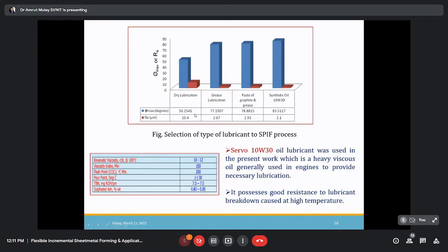Now you can see that when we compare these results, different lubricants we tried in the CNC machine, with a given set of parameters, synthetic oil gives more phi max. More phi max means more formability, because it is a varying wall angle conical frustum. So at what maximum angle is it going to fracture? The maximum value is 83.51, which is the highest among all, and surface roughness is lowest among all. It means that we understand from this that 10W30 will be good for CNC operation.